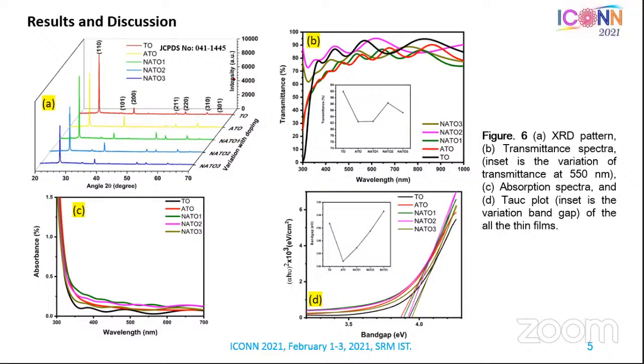So coming to optical properties, this is the transmittance and this is the absorbance. In transmittance, pure tin oxide shows the highest transmittance. When we dope with antimony, it decreased. Then by co-doping with niobium, it slightly increased. For 2%, it increased up to 85%. Then again with 3% doping of niobium, it decreased.